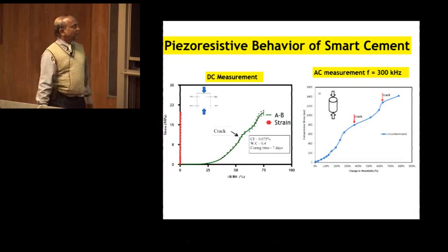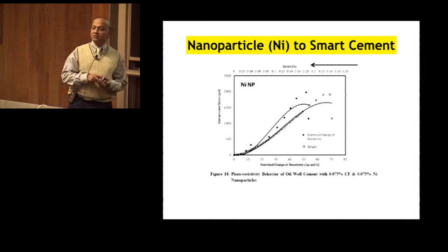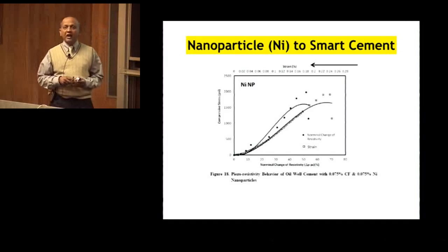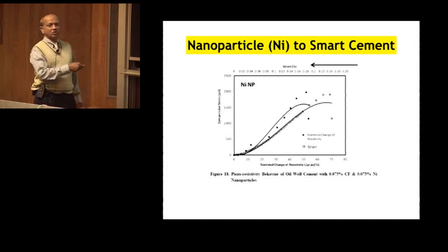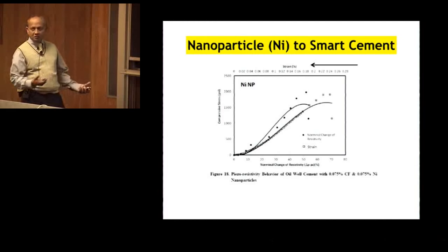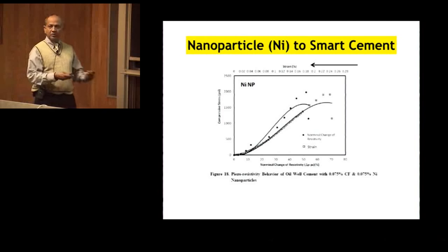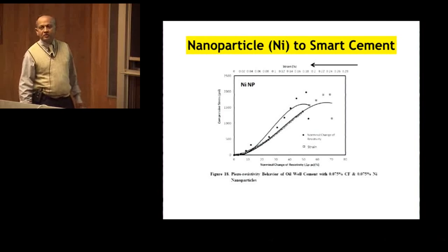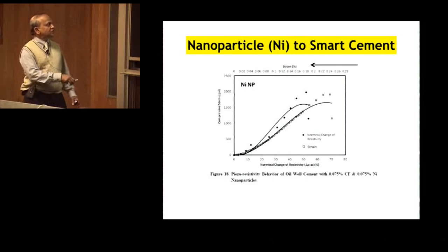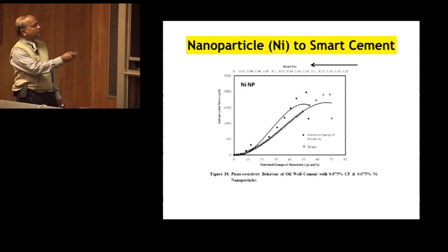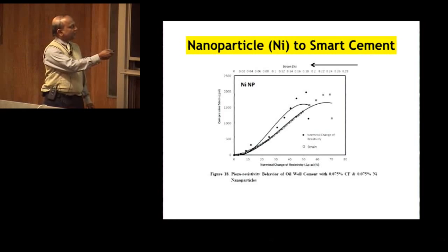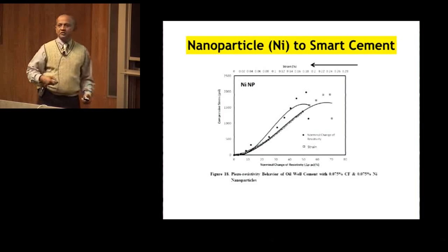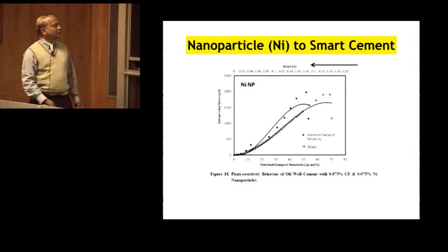And then also, as I told you, we work on nanoparticles and nano additives. Just to show you some typical results, we are looking at some metallic nanoparticles, because depending on the environment, people like to use different things. And we want to see how sensitive the material is. You can see this part is giving you the strain. We measure the strain, and also we measure the resistivity. The failure strain is around 0.2%, as I told you, whereas the failure resistivity change is around 60-70% or much more, depending on the mix you have.